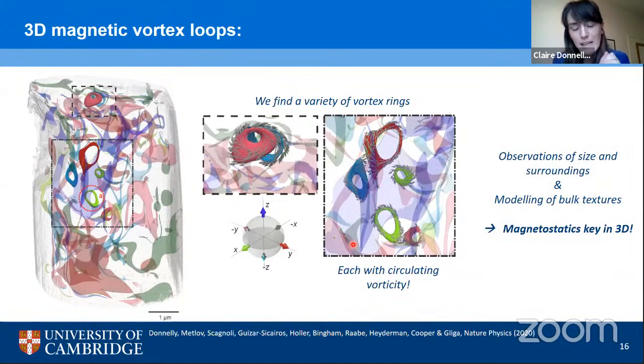And by a combination of looking at the size and the surroundings of these different vortex rings and performing modeling of bulk textures such as cross-tie walls, which was done by our colleague Konstantin Metlov, we are able to determine that the key to the stability of these vortex rings is the magnetostatics. Now, this is particularly important because when we think about three-dimensional structures, and often their analytical modeling, magnetostatics are not always taken into consideration because, understandably, they're very hard to calculate analytically. These observations indicate that the magnetostatics seem to be more important than we perhaps realized, and something that could be really important for future studies on topological and non-topological structures in 3D.